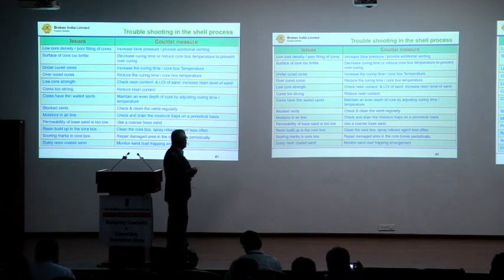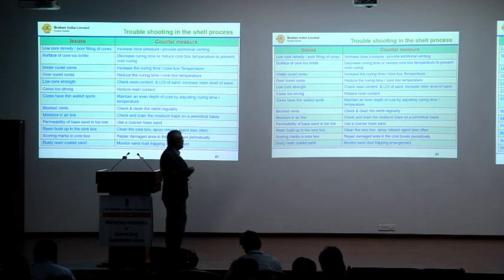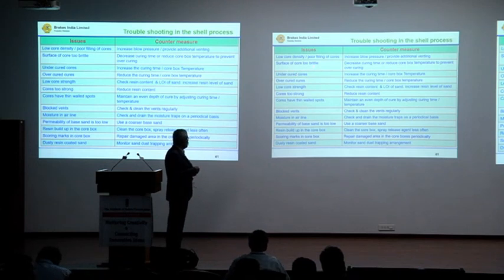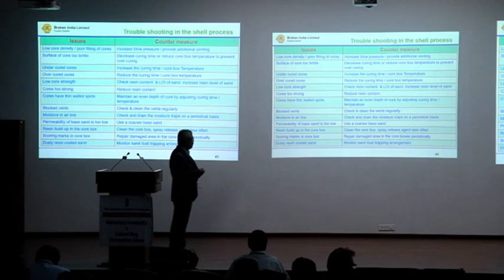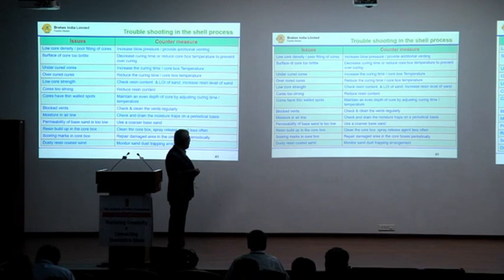Low core density or poor filling of cores is probably due to low blow pressure - increase it and provide additional venting. If the surface of the core is brittle, increase curing time or reduce core box temperature to prevent over curing. For an under-cured core, increase the curing time and core box temperature. For over-cured cores, reduce the temperature and curing time.